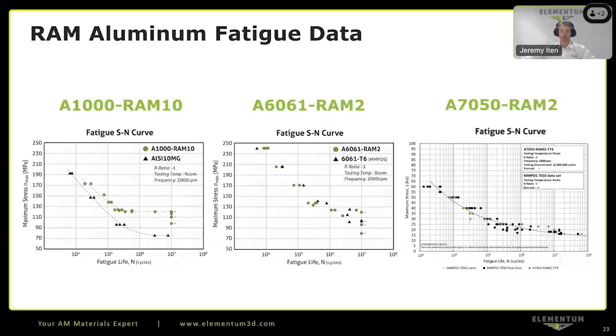These points on the very right are all run-out points where basically the test was stopped without the parts failing. And on the very right, you see 7050 RAM 2 material also compared against the MMPDS aerospace data set. And again, the printed RAM 2 material compares quite well in fatigue.